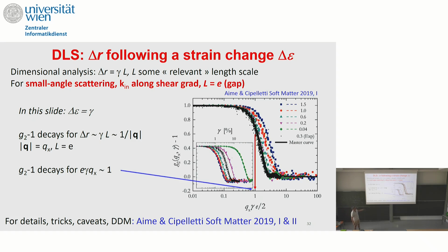This has been measured by deforming a nearly ideal elastic solid. You take data measured at different Q vectors, but all along the QX direction of the imposed shear, and you can superimpose most of them if you rescale the imposed strain by the thickness of the sample, because what really matters is how thick the sample is.